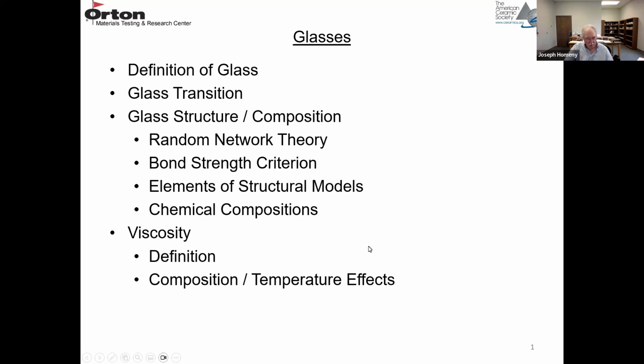We had mentioned that a typical refractory microstructure consists of crystals, glass, and porosity. So we went over crystal structures. We talked about ionic and covalent bonding, and ions that have high charge and small size are going to result in strong bonding, which translates into high melting temperatures, which is important for refractories. And we looked at some of the different common crystal structures for some typical refractory materials. So crystals are one aspect of the microstructure, and so are glasses.